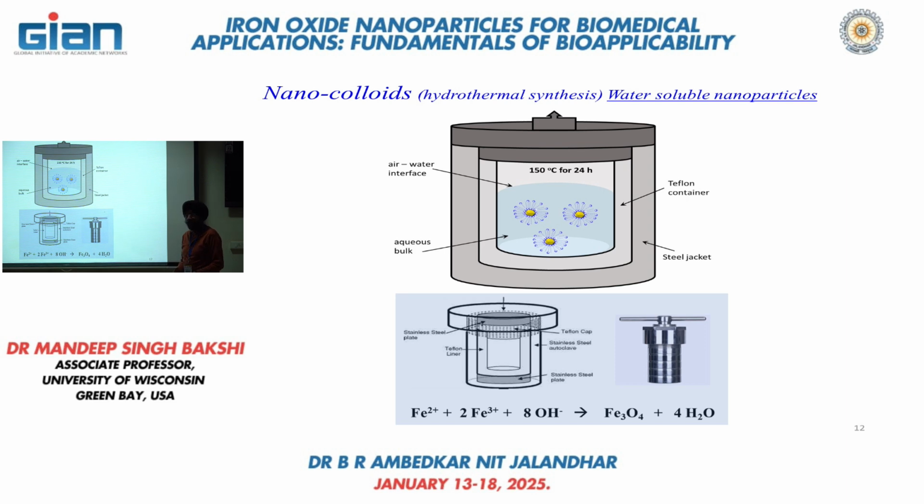well-defined iron oxide nanoparticles unless, after completing the reaction, you place it in a steel container including the Teflon container placed in a steel jacket. So here is the Teflon container. Teflon is non-reactive, and here you have the steel jacket, and there is a steel cover. You can tighten it. You perform the reaction at room temperature, pour the contents into the Teflon container, and tighten it. Now you place this at 150 degrees centigrade for 24 hours.